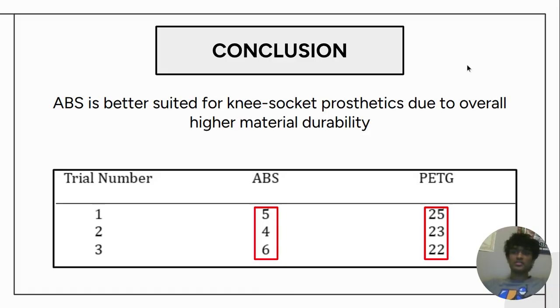In terms of a conclusion, overall, ABS is better suited for knee socket prosthetics because of its overall higher material durability. A key finding is ABS in the tensile strength test only displaced about 5, 4, and 6 millimeters, where PETG displaced about 25, 23, and 22 millimeters. Also, ABS was better suited in terms of warm temperatures and water absorption.